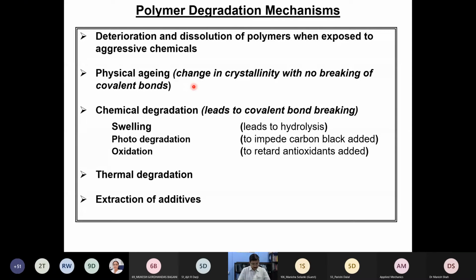For example, in some cases the base of the geomembrane and GCL was subjected to temperatures where, even though the groundwater temperature is very close to 10 degrees in the North American region, the temperature might have gone up to even 55 degrees. That means the polymer is aging at 55 degrees centigrade, no more very close to 10 or 20 degrees. Also, in the process of manufacturing, we add a lot of additives and stabilizers to enhance manufacturability or service life. These additives also get extracted out of the polymer over a period of time, which is another possible degradation mechanism.